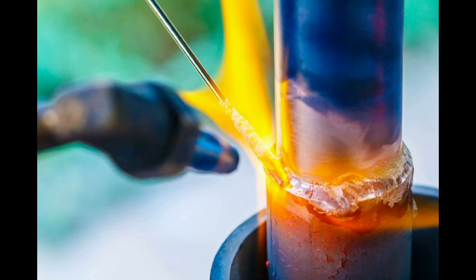Use of a slightly oxidizing flame is more specialized. Typical uses are for welding copper and zinc-based metals or manganese steels. In these cases, an oxidizing flame creates base metal oxide that protects the base metal.